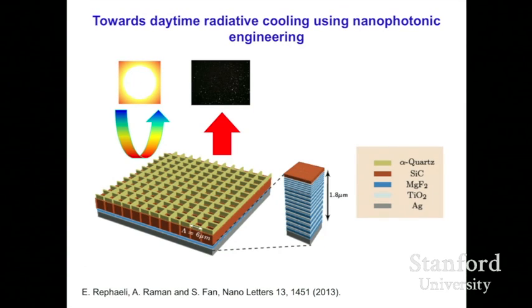So our specialty is in designing optical structures with unusual electromagnetic properties. Therefore, we set out to design something that looks like this in its emissivity profile. And this is our initial theoretical construction out of a simulation. And in order to provide a broadband reflection of sunlight, we envision a multi-layer structure, in this case theoretically made of magnesium fluoride and titanium dioxide, with a chirped periodicity to give you broadband solar reflection. On top of it, we put in materials such as silicon dioxide and silicon carbide with thickness on the order of a micron.